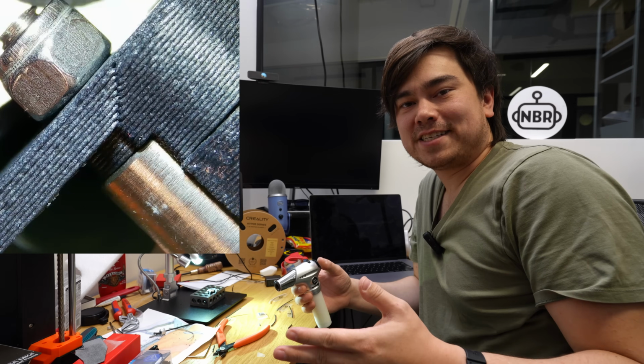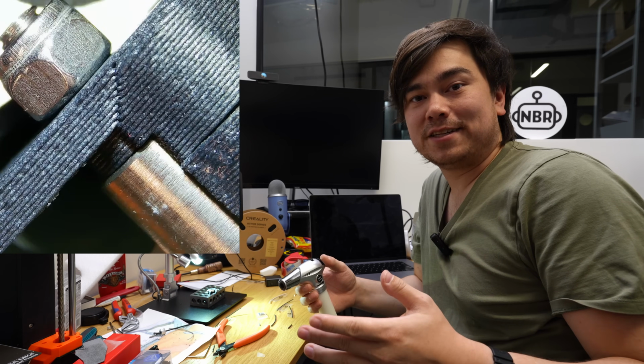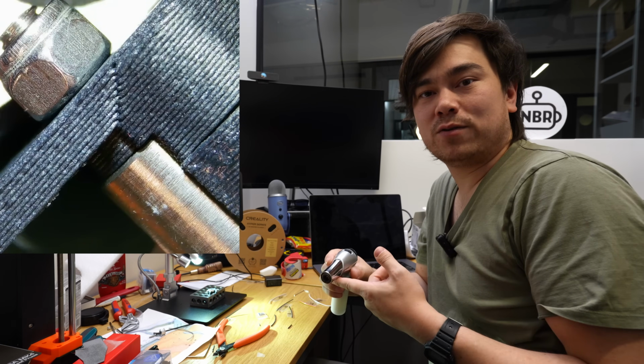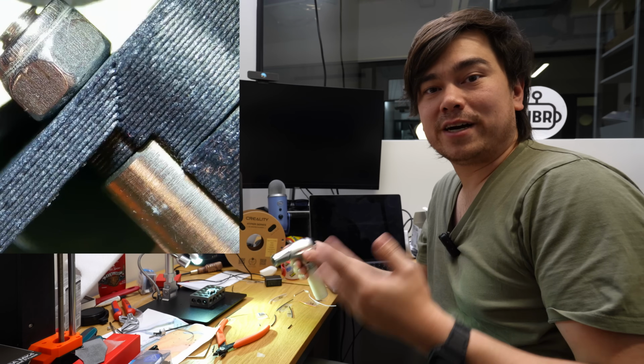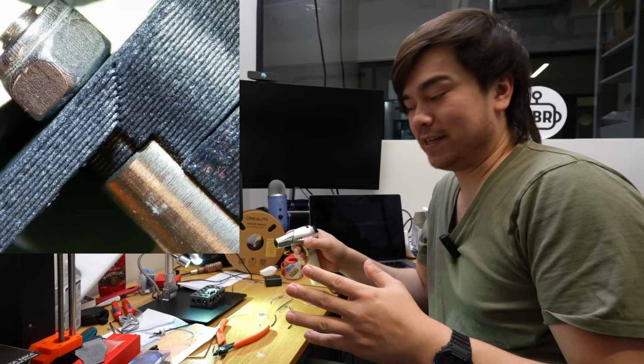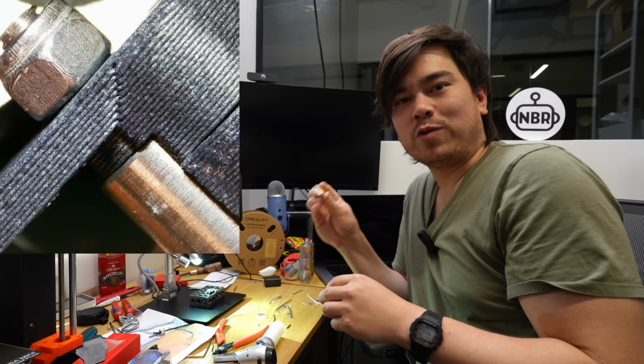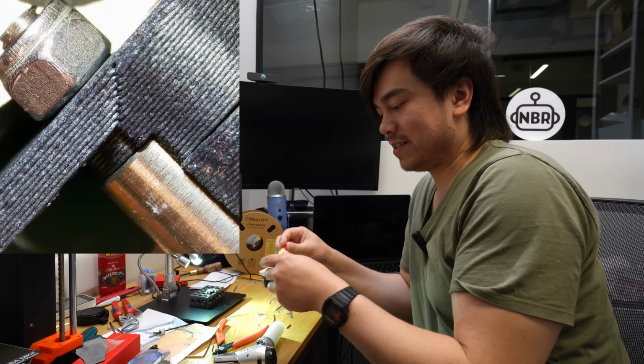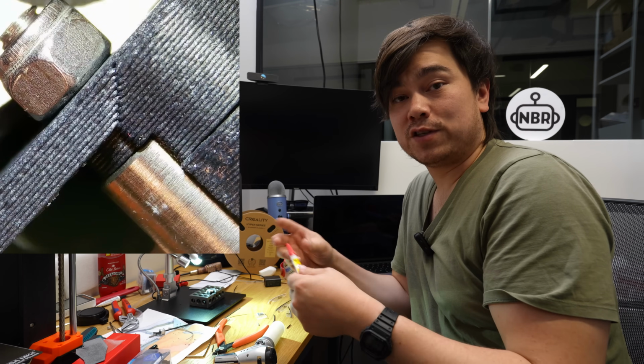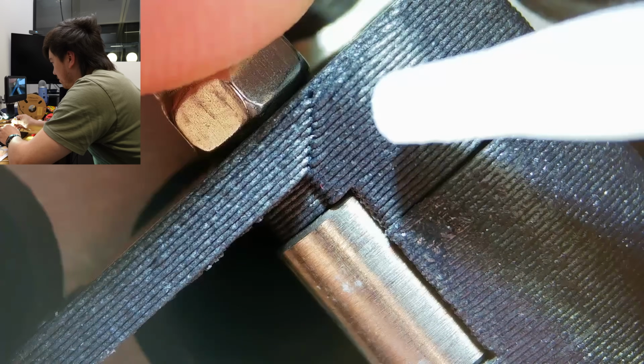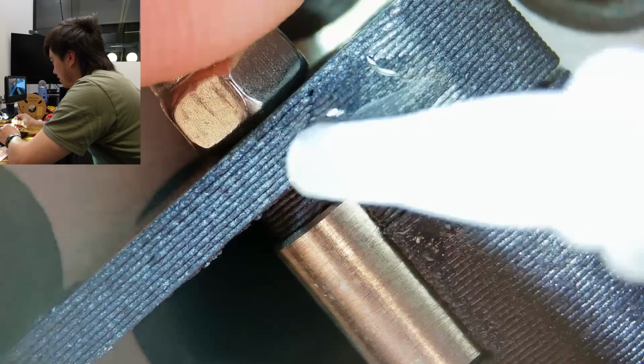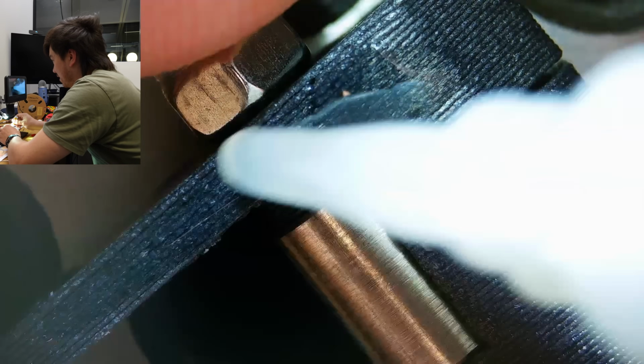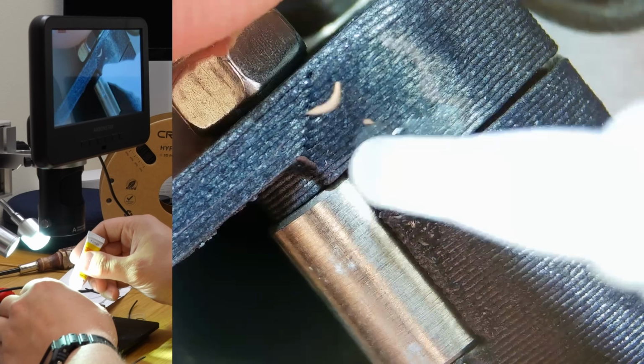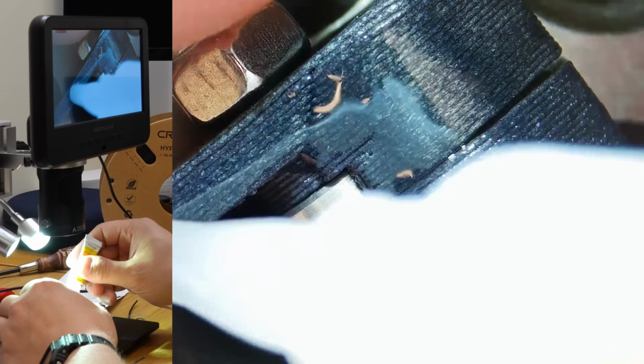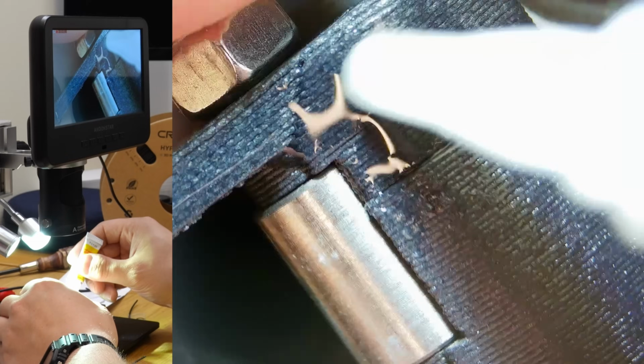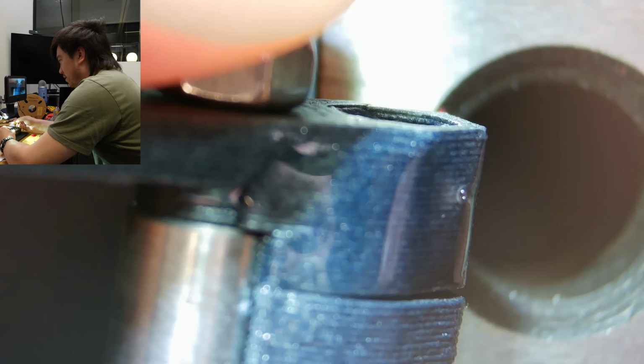Okay, so we've clearly established that there's a problem when handling these materials, whether it's the filament or printed parts. You have to be cautious about the fibers coming off of these things. Probably the simplest and cheapest way of applying a clear coat on small parts like this, if you have a tube of super glue around, you can just use that. We just apply it to the surface and wet everything down. And that will encapsulate all your fibers. You don't have to worry about them coming loose. Just like that, everything's coated in super glue.